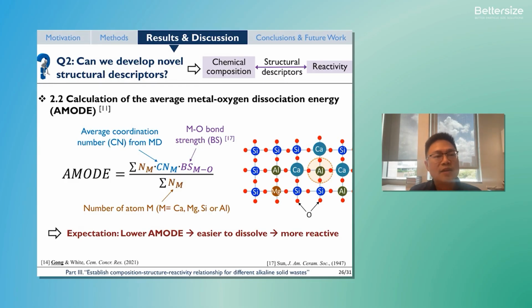You can understand this equation in this way. Say we want to dissolve, for example, aluminum oxide from the waste material. We need to break all the aluminum oxygen bonds. This BS, bond strength parameter, essentially tells us the energy that is required to break a single aluminum oxygen bond. And this coordination number, CN, tells us how many of these aluminum oxygen bonds we need to break in order for a single aluminum atom to dissolve from the structure. And these N parameters at the bottom essentially tell us the number of aluminum atoms we have in the system.